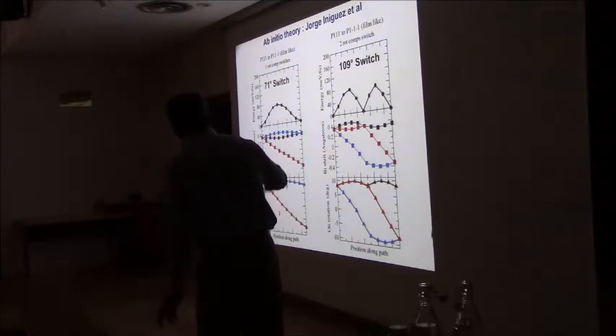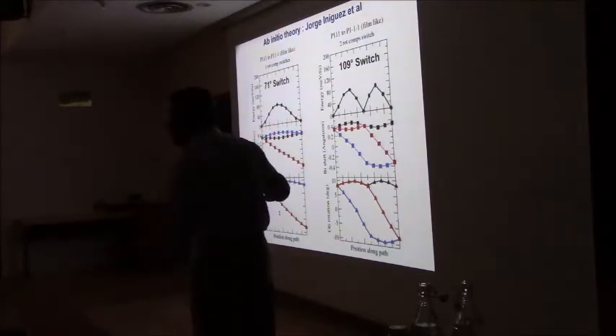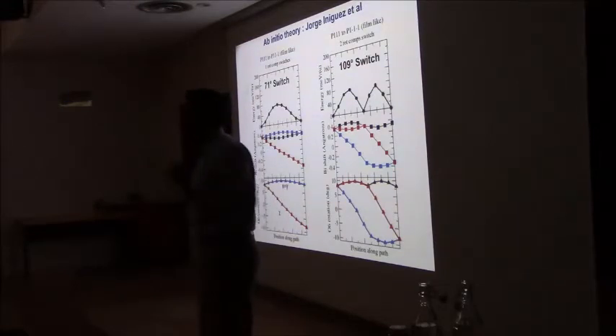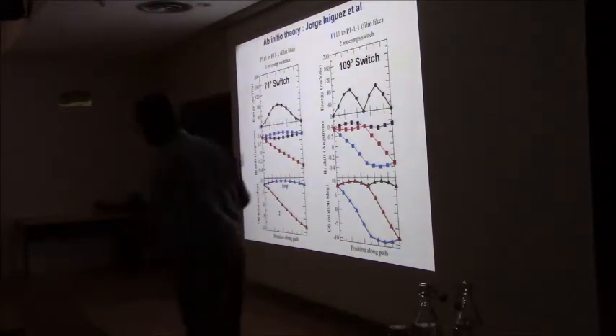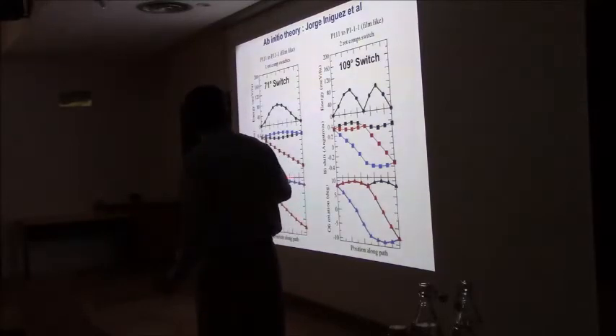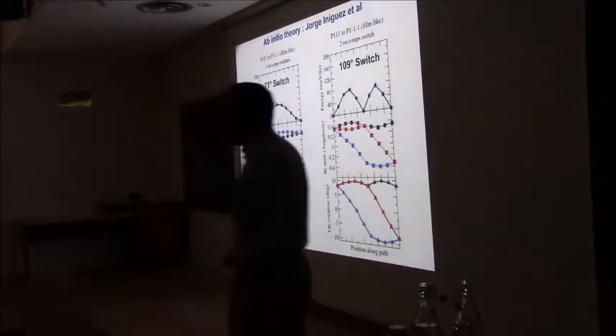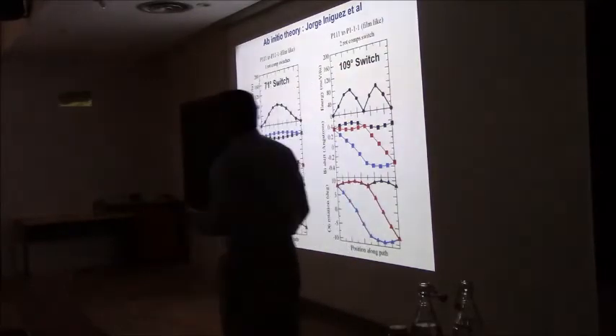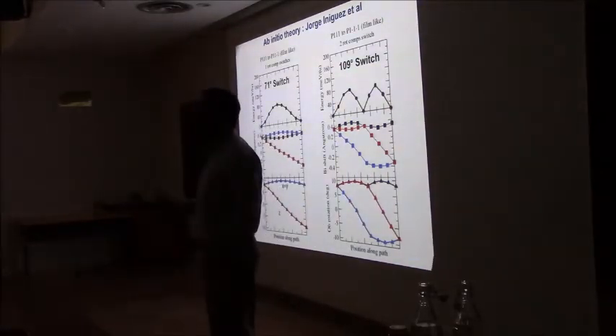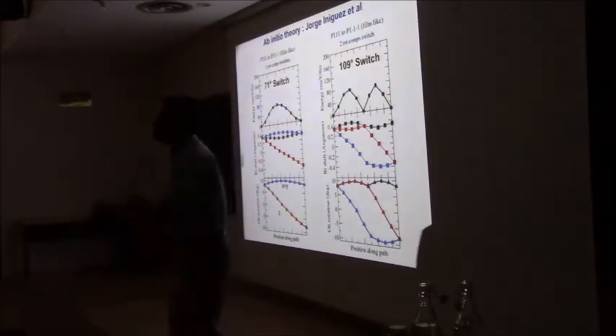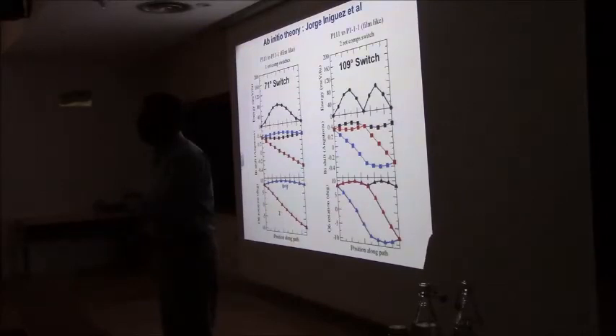Let's look at these two parts. The bismuth ion shift, clearly the red is basically the Z component, and the blue and the black are the X and Y components. This one changes sign, but these two don't. But he found the octahedral rotation, which is directly related to the magnetism, the canted moment, changes sign for the Z component, but not for the X and Y. So Jorge's claim was that, hey, you have to look at all states. And I was saying, dude, I don't know if I believe this, but it took us a while, and all of our experiments were telling us that Jorge was right.